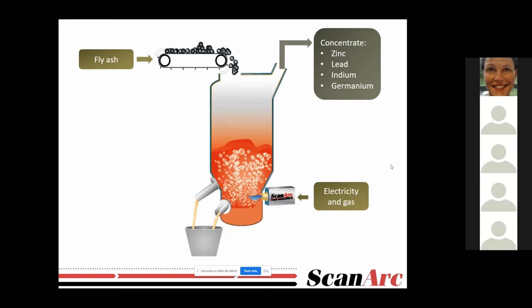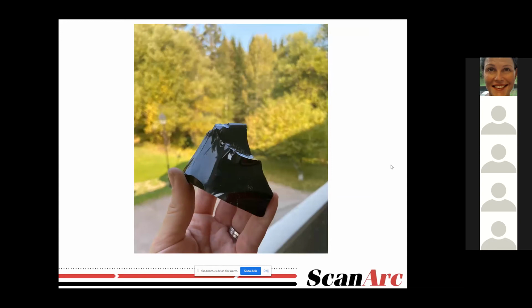We can extract at least 90% of the zinc and 95% of the lead, and it depends on the ingoing content in the fly ash. The more metals in the ingoing content, the stronger the driving force is to extract the metals. And when we have done this, what is left, we tap the furnace and we let it solidify, and we then have this glassy material.